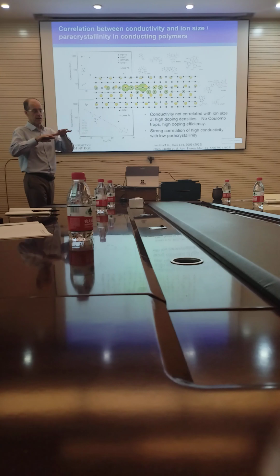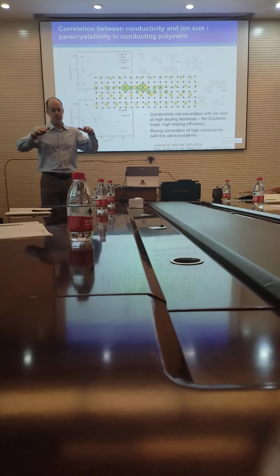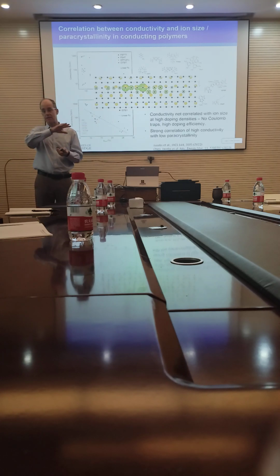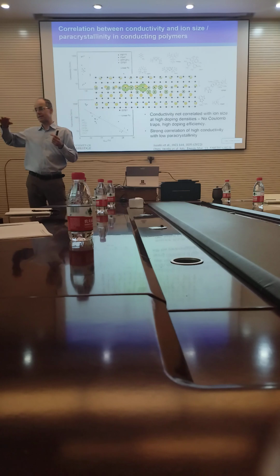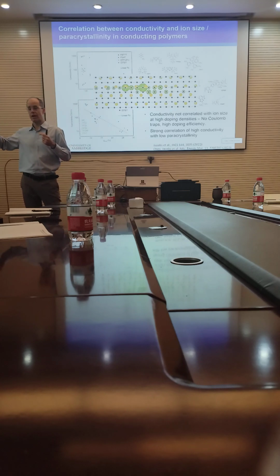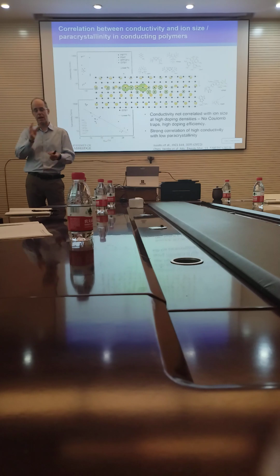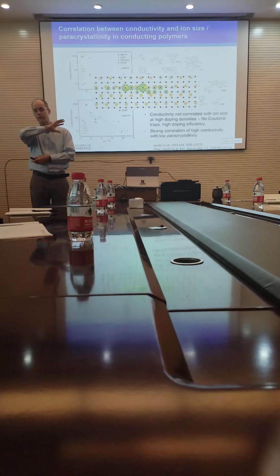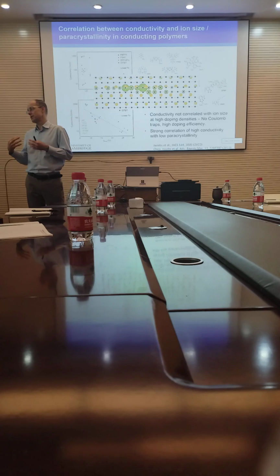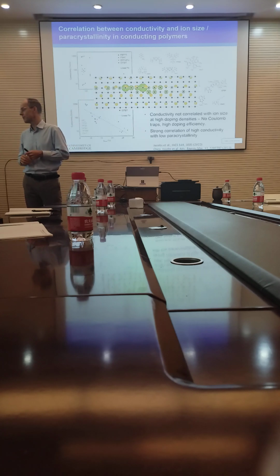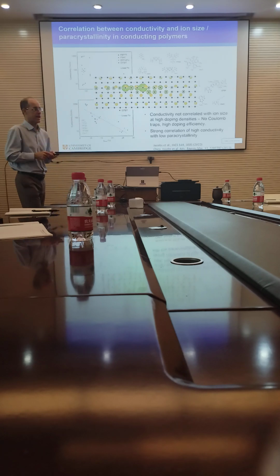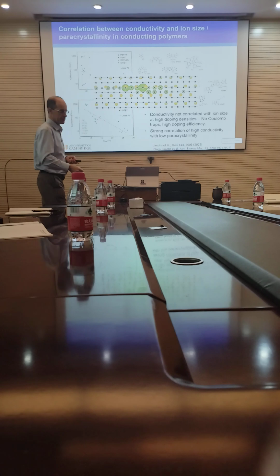And that means that the electron wave function is able to average very effectively over that Coulombic landscape that the ions generate. So whether you have a small counterion or a large counterion, the electron is just averaging and smoothing that landscape very effectively, and that's why the conductivity is not dependent on the ion size. So that's the first lesson that we learned by looking at these quantum systems.